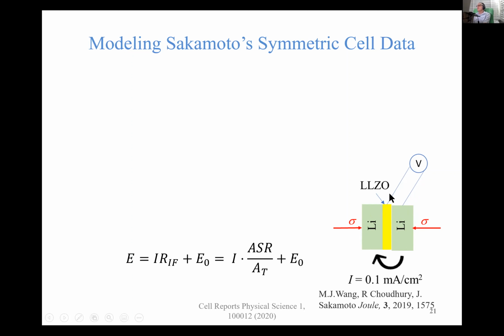The voltage drop that he measures is going to be equal to the voltage drop across this interface. That's this R sub IF we talked about. And that voltage drop is just going to be the current times that interfacial resistance, plus all the other voltage drops in his system, which we're going to treat as constant. So remember, this interfacial resistance looks like the area-specific resistance divided by the true contact area, which might change.